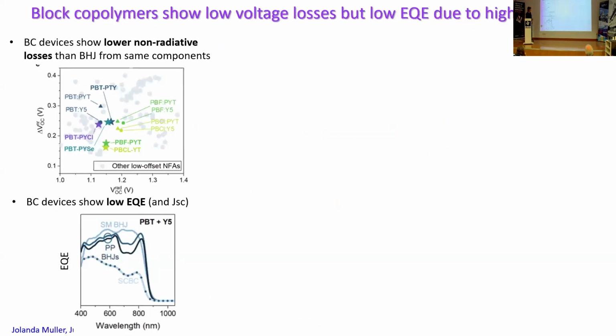And we did. And we found that the voltage, I mentioned, tends to increase. And we see that that's associated with a somewhat smaller voltage loss. The current tends to decrease. That's reflected in a smaller external quantum efficiency.